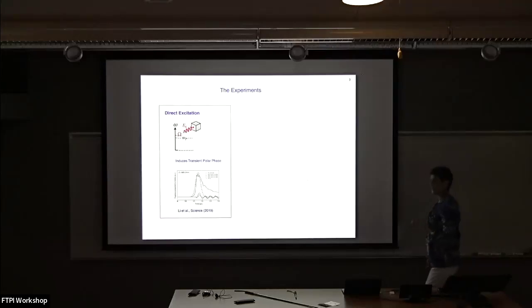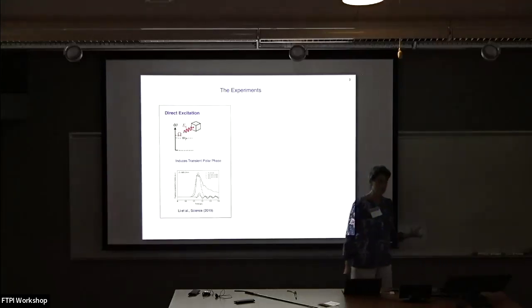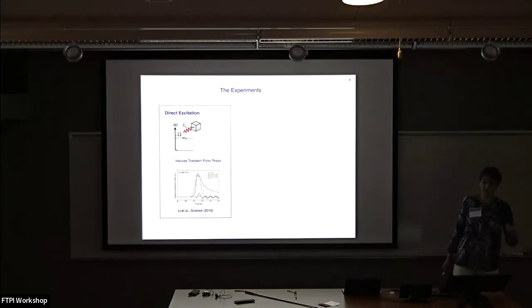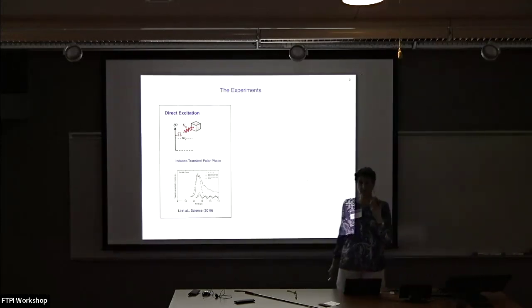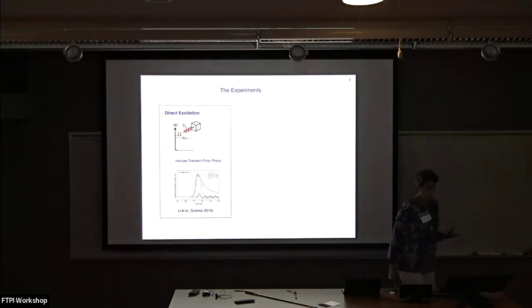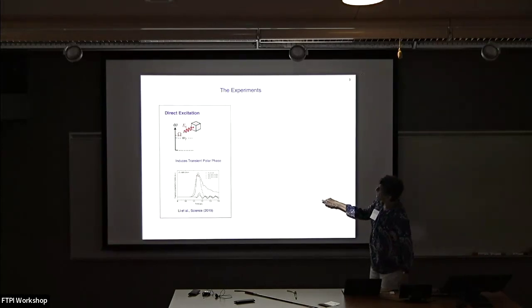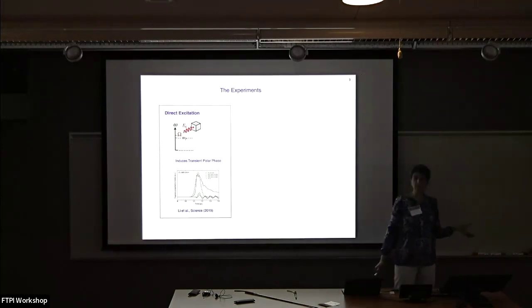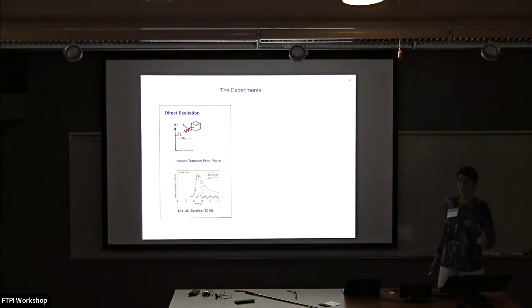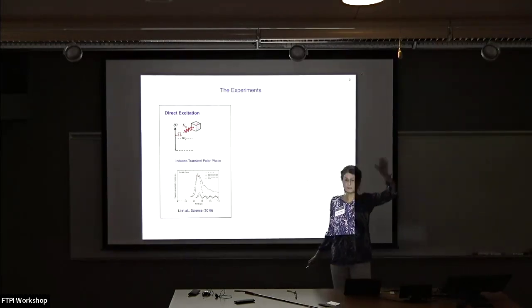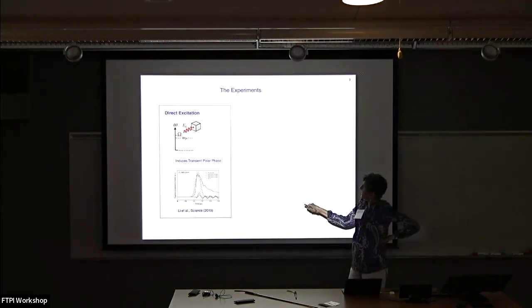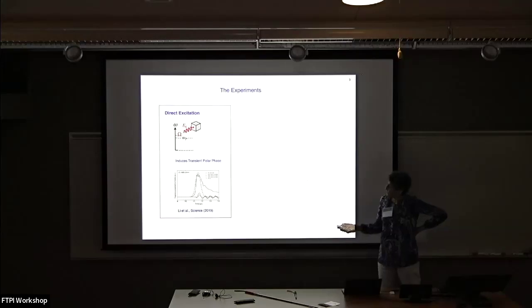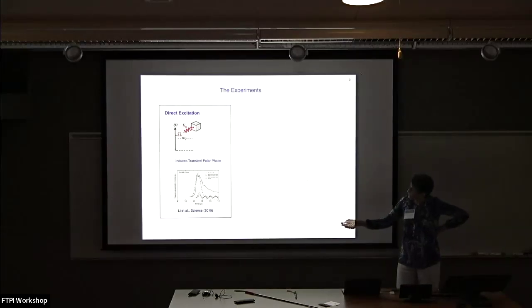So as you know, strontium titanate is a system that's very close to being ferroelectric, but it's rebellious. That's why I like it so much. Okay, it's stubborn. However, it has a polar mode that, as we saw from the previous talks, refuses to go soft. That's why the dielectric constant saturates. And what they did was they resonantly pumped this mode.